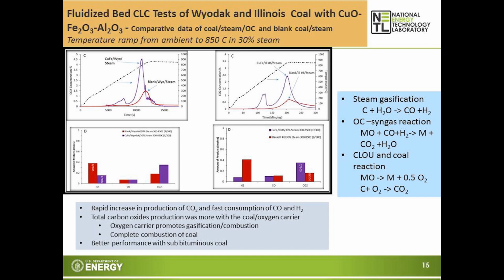So this indicates that the oxygen carrier enhances the CO2 production, and also the amount of CO2 produced is significantly higher when the oxygen carrier is present. And so the oxygen carrier promotes the coal gasification process and also the subsequent combustion process. We saw similar behavior with the Illinois number 6, but the rate enhancement was more significant with the Wyodak coal.